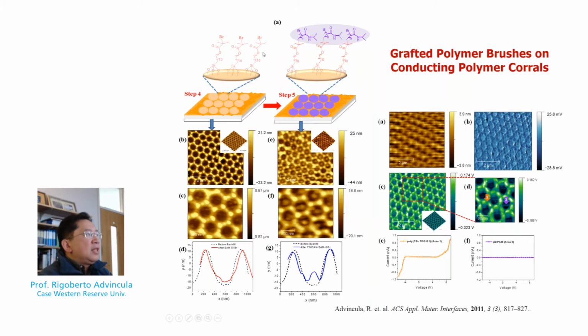We grafted an ATRP initiator in between those holes, and then we grew a poly-NIPAM brush within those holes. And you can observe by the atomic force micrograph how the holes have been modified with the polymers in between. Now, a conducting AFM technique actually allows us to distinguish between the conducting polymer arrays and the non-conducting polymer brushes that were grafted on the surface, resulting in a difference in the color density or pulse color map, as well as differences in the heterojunction behavior.